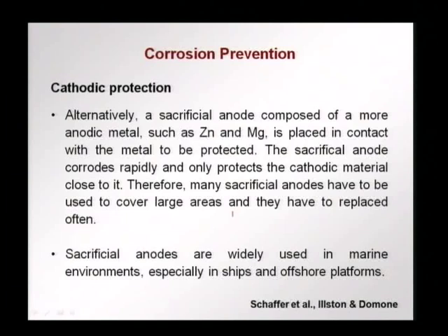Sometimes we have that even in reinforced concrete, to protect the reinforcement we embed these sacrificial anodes in the cover, so that they can be sacrificed and protect the reinforcement, which if it corrodes can lead to failure. Sacrificial anodes are widely used in marine environment, especially in ships, offshore platforms. It is systematic to put pieces of zinc or magnesium in contact with the steel, so that they can corrode, and they are periodically replaced and protect the steel in the application that we want.